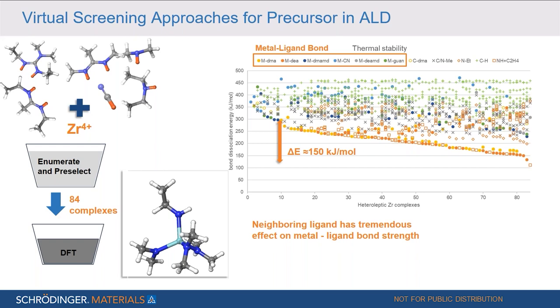So in this particular example, 84 zirconium complexes were generated automatically by automated permutation algorithms, and the bond dissociation energy was computed using density functional theory calculations. And the results are shown here in the right-hand graph. What we can see is that the x-axis shows the different complexes ordered with regard to their bond dissociation energy, and the y-axis shows the minimum bond dissociation energy for the complex. And the filled circles denote the metal ligand bond dissociation energy for the different ligands.